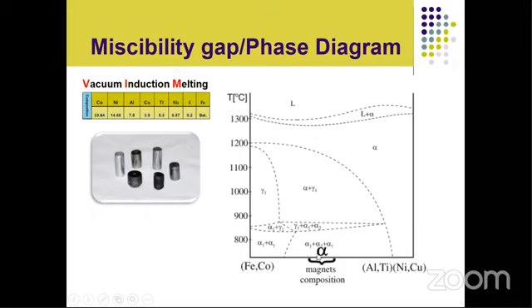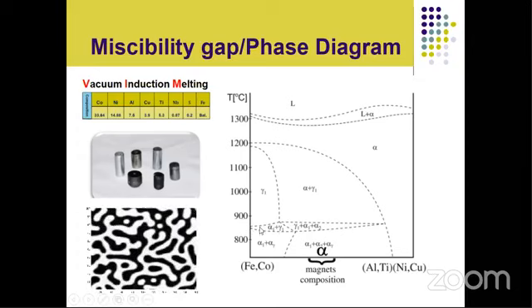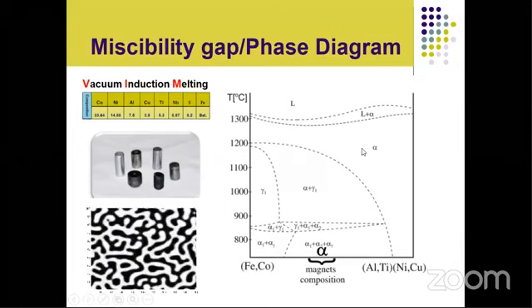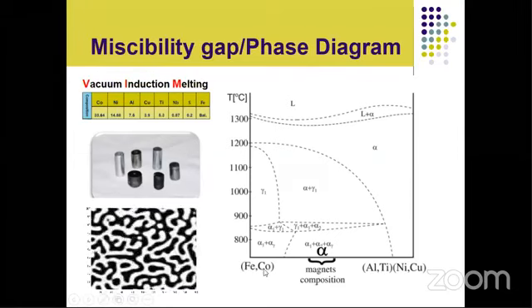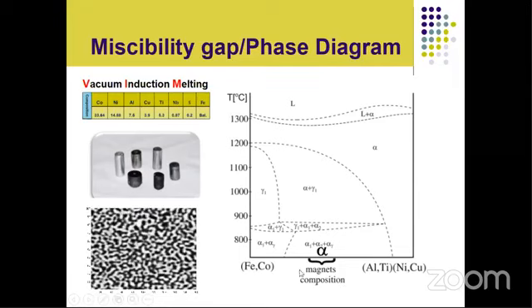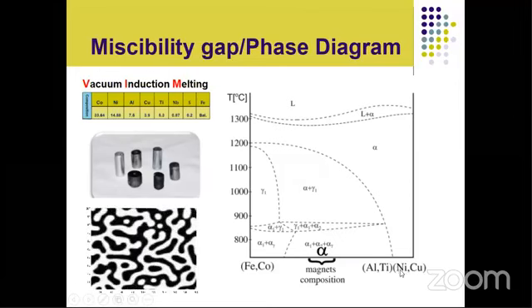But when we quench this material, it will come across this region. This narrow region is very important. It is very close to the Curie temperature of the material. When we quench this material from the single phase, which is alpha 1, definitely below the liquidus, in this region the material splits into two phases. We will call them alpha 1 phase and alpha 2 phase. Normally, alpha 1 phase is iron and cobalt rich, and alpha 2 phase is nickel and copper rich. It means this one is more ferromagnetic and this one is less ferromagnetic. But in the iron and cobalt phase there may be some nickel and copper present, and on the other hand, in the nickel-copper rich phase we may have some iron and cobalt.